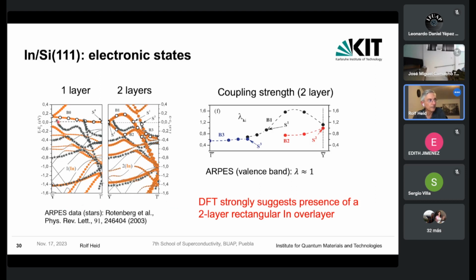And you see here the ARPES data, which are given by these stars. If one compares that with the band structure of a 1 layer system, where the light red bands are indium type bands, you see hardly any agreement in this case. But here you find nice agreement with many of the calculated bands. So also from this calculation, we would say the experiment is really measuring a 2-layer system.